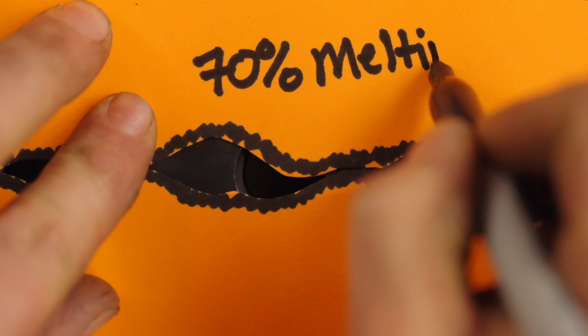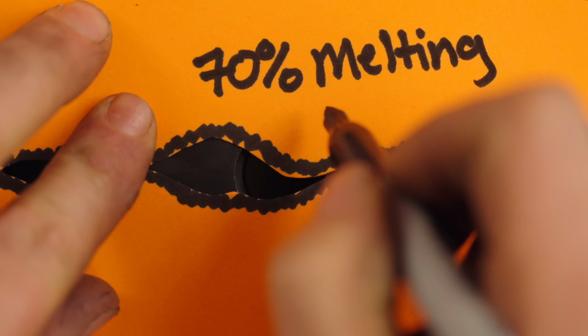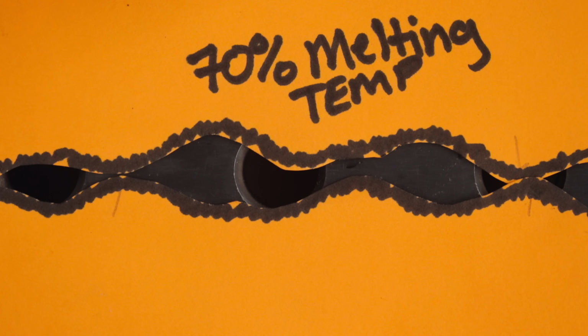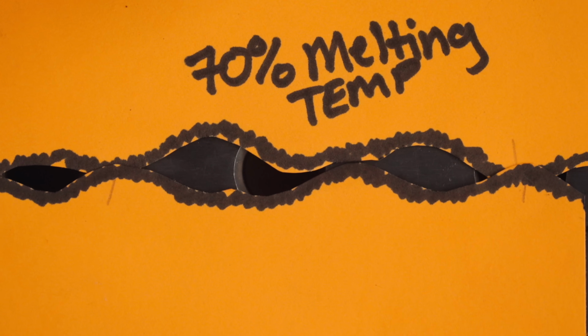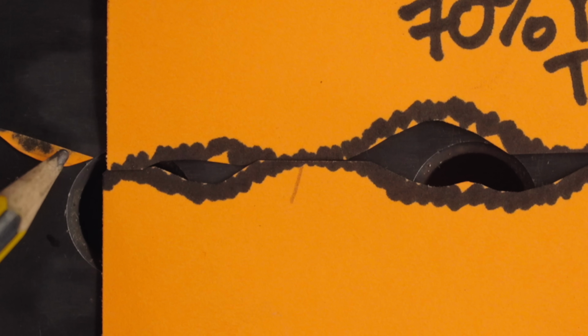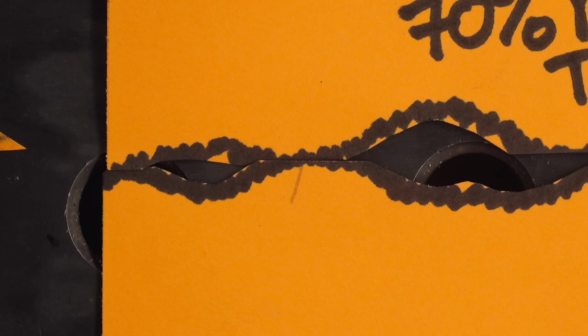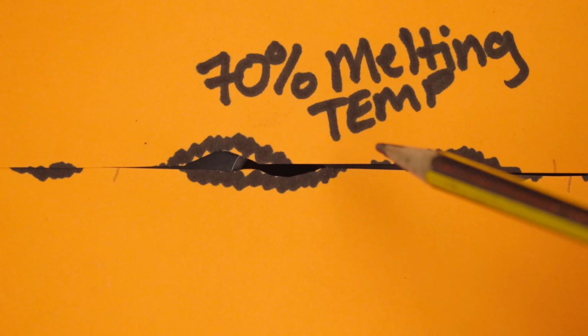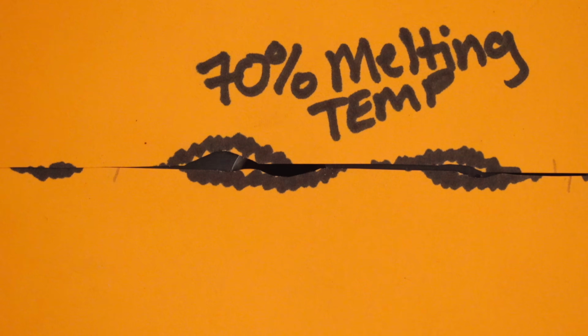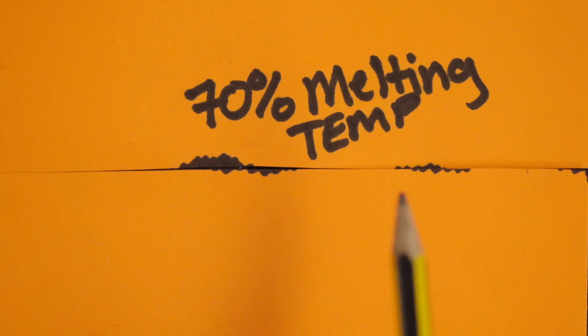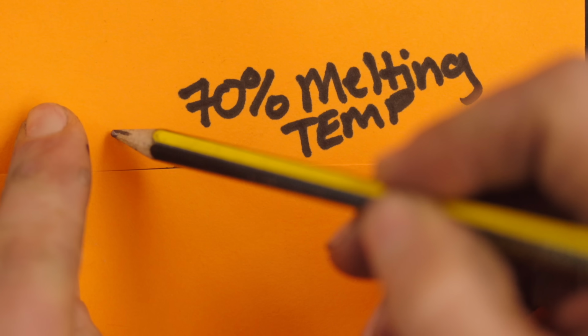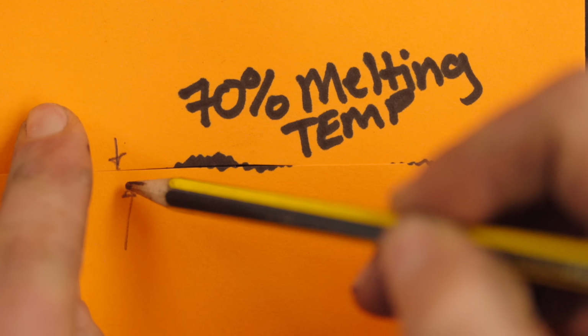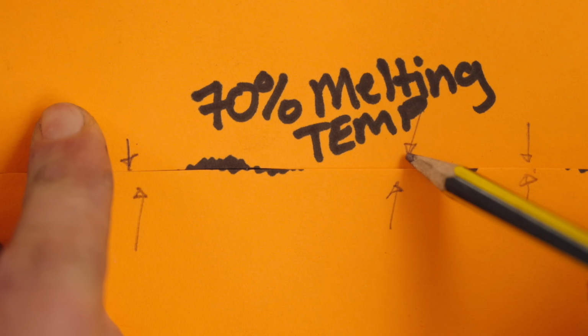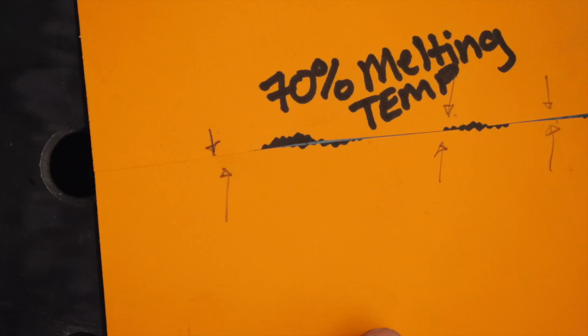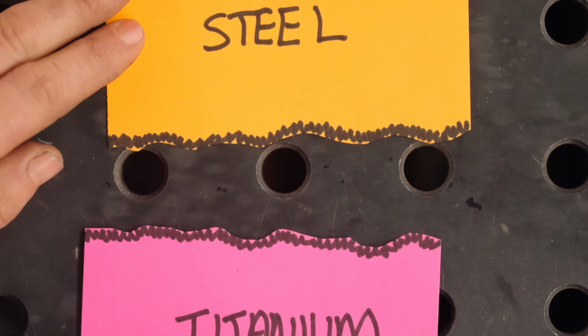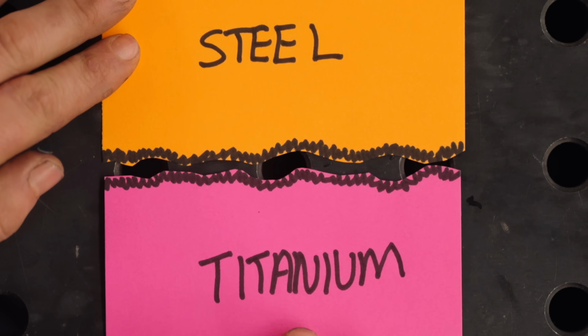And so, when you heat the metal to something like 70% of its melting temperature, it's easily able to experience plastic deformation as pressure is applied. That deformation shatters the brittle oxides and sends them on their way. The amount of true metal-to-metal contact increases, and eventually across the joint, with as few inclusions as possible, the excited atoms on either side of the interface are able to intermix and diffuse between themselves and be bonded as if one piece. So why is it so bloody difficult to bond steel to titanium?